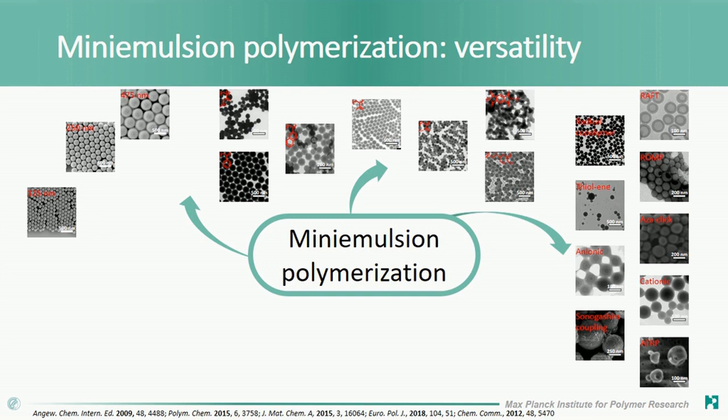And it's also compatible with different polymerization processes, whether it's RAFT, ATRP, anionic, cationic, and all kinds of different cross-coupling, from Sonogashira coupling to make new carbon-carbon bonds, to thiol-ene, or the addition of an azide with an alkene. All these types of reaction have been done in miniemulsion, and basically most chemical reactions that we could do in bulk could also be done in miniemulsion in some way or the other.